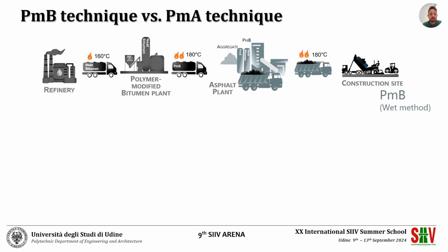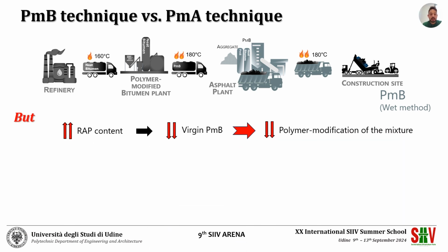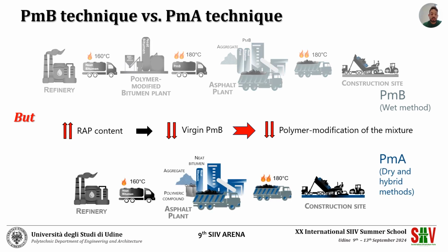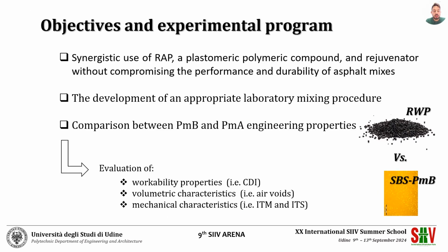This is the process to produce and use PMB in asphalt mixtures. However, increasing the RAP content leads to less virgin PMB in our asphalt mixtures, and so less polymer modification of the mixture. For such a reason, the PMA technique tries to overcome this problem because the polymer is directly added to the asphalt mixture.